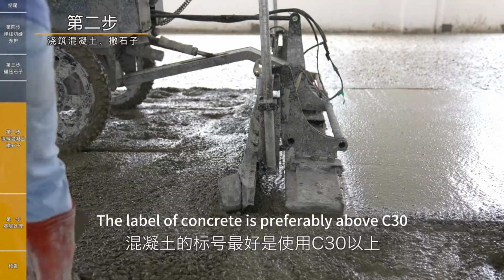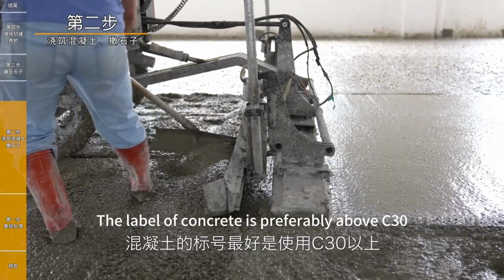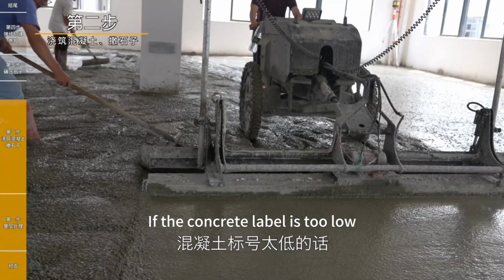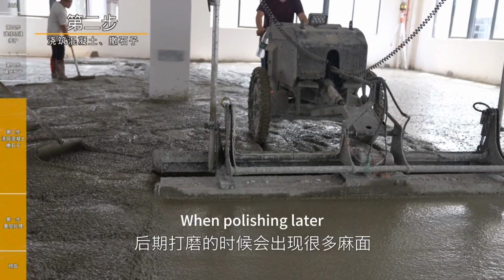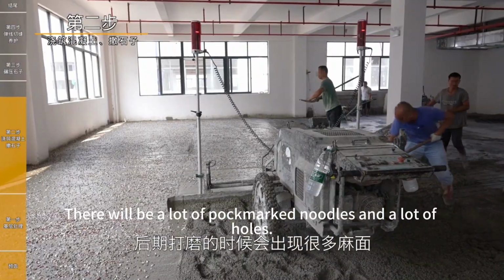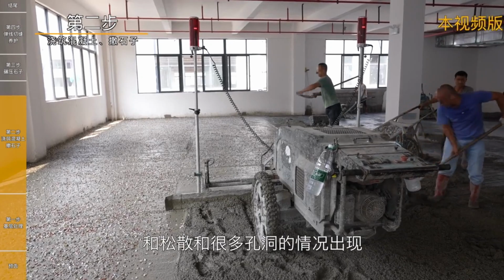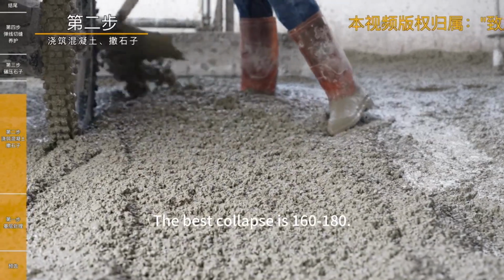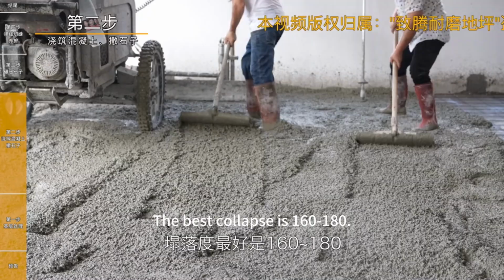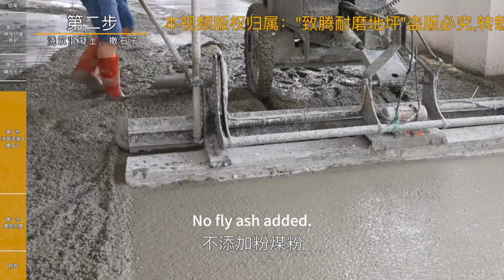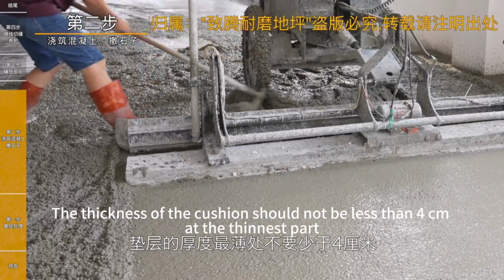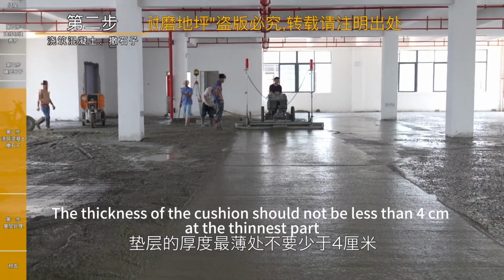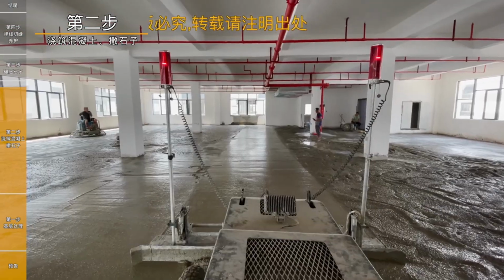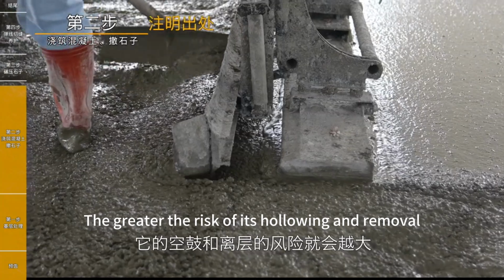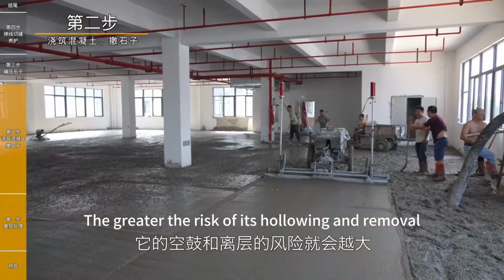The grade of concrete is preferably above C30. If the concrete grade is too low, when polishing later, there will be a lot of pockmarks and holes. The best slump is 160 to 180, with no fly ash added. The thickness of the cushion should not be less than 4 centimeters at the thinnest part. The thinner the cushion, the greater the risk of hollowing and delamination.